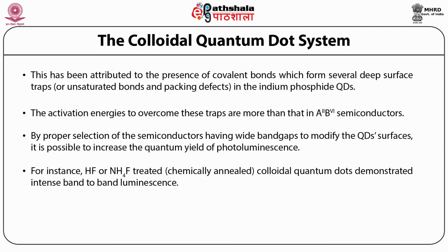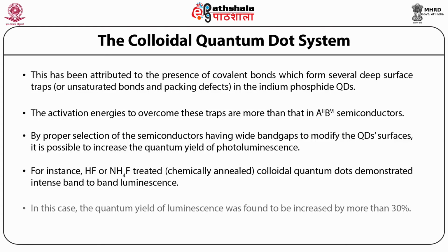For instance, HF or NH4F treated chemically annealed colloidal quantum dots demonstrate intense band-to-band luminescence. In this case, the quantum yield of luminescence was found to be increased by more than 30%.